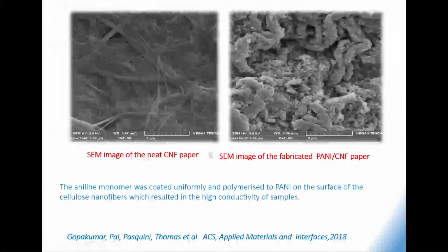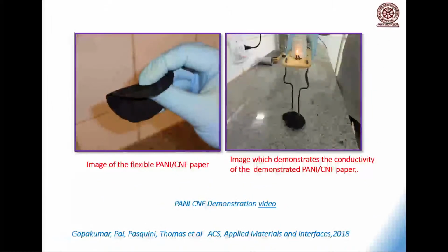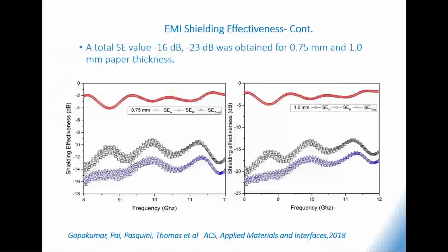And you can see this is neat nanocellulose, and this is aniline polymerized on the surface of nanocellulose. So we made a conductive network of aniline on the surface of nanocellulose. You can see the sample we have made. Very lightweight and conductive. And you might ask, what is the use of this material? This is a beautiful electromagnetic shielding material.